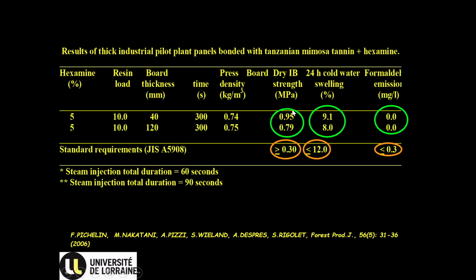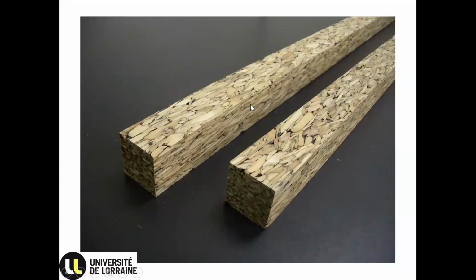And you can see the dry internal bond strength in megapascal is very good, better than the Japanese standard. The 24-hour cold water swelling is better than the Japanese standard, that is the most severe that still exists. And the formaldehyde emission was 0.0. In the pressing time, if you look at 300 seconds and 300 seconds, you know what I mean, it is very good for boards of 40 millimeters, 120 millimeters thick. They cut the board into these beams that are used to support Japanese wooden houses.